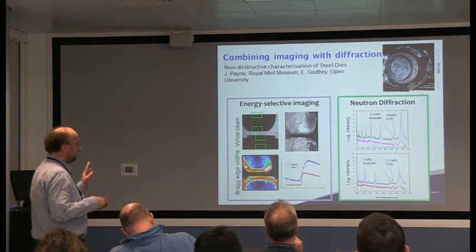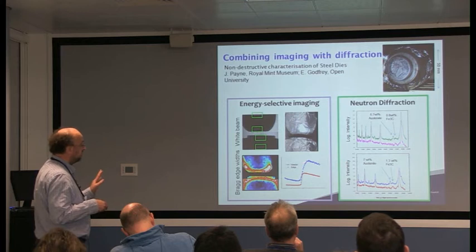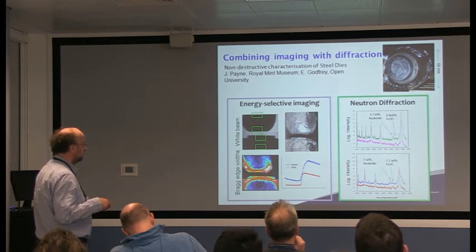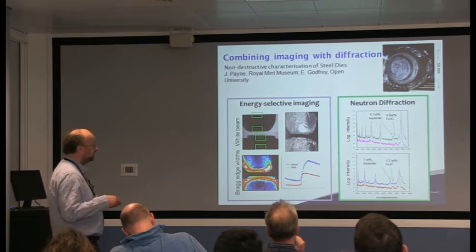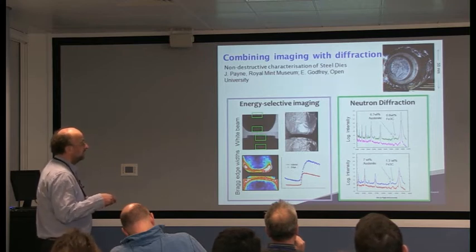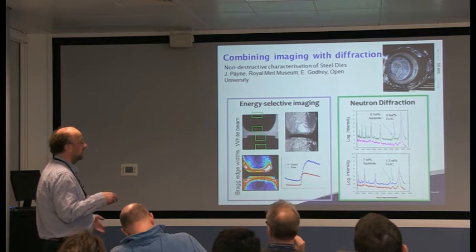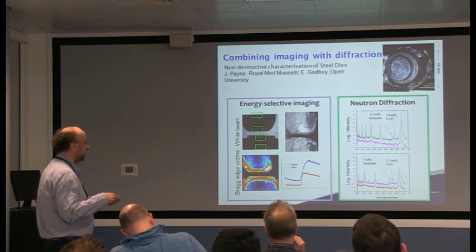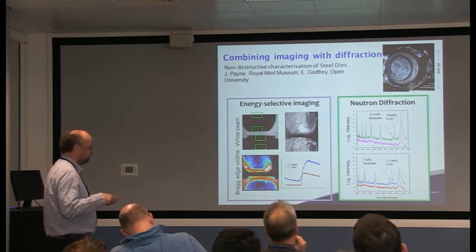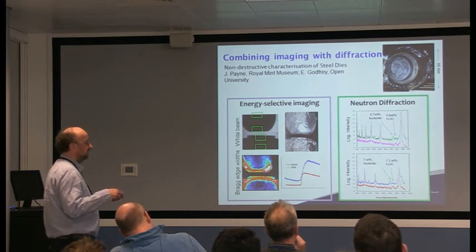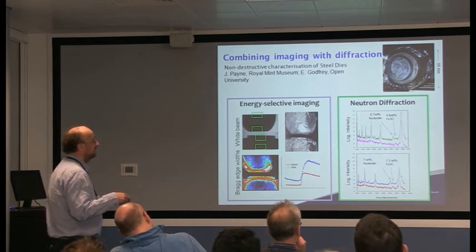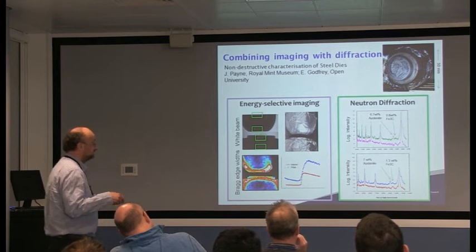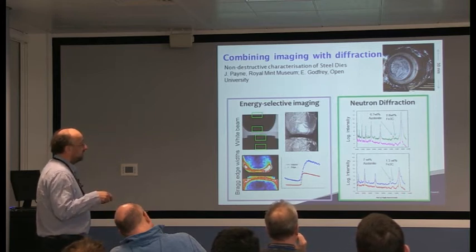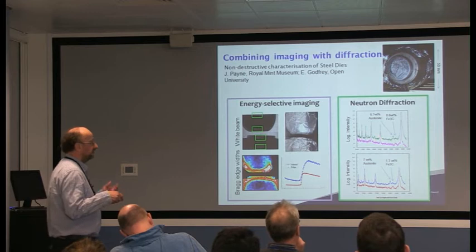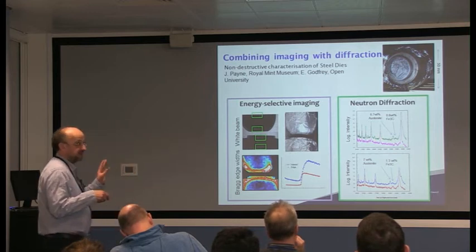We collect kind of the complementary information in the diffraction data. We again see this martensitic to ferritic transition. We also pick up other details in the diffraction, like extra phases, the austenite or the iron carbide phases, which we don't see in the imaging. And it's actually just a question of concentration. So here my point, and that is also the purpose of IMAT, will be that we need actually both.